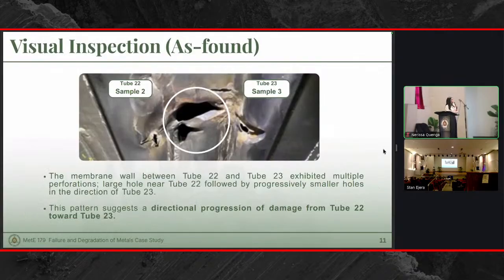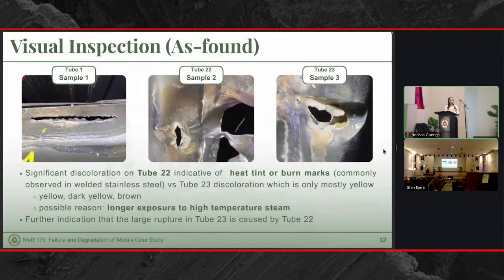Upon closer look, the membrane wall between tube 22 and tube 23 exhibited multiple perforations, and these perforations gradually became smaller as it approached sample 3. So this is evidence of a directional progression of damage from tube 22 towards tube 23. Moving on, we can also notice some discoloration on both sample 2 and sample 3.